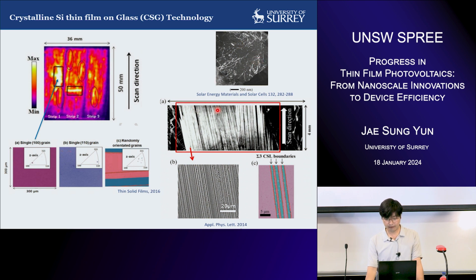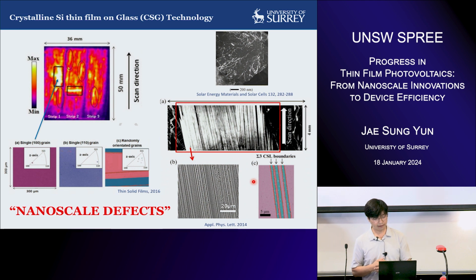Also, I found out that there are a lot of twin boundaries if you crystallize your materials with the laser crystallization method. And there were a lot of sigma 3 CSL boundaries, and I tried to investigate what their impact is on the performance. So I've learned that nanoscale defects play a very important role in polycrystalline materials.